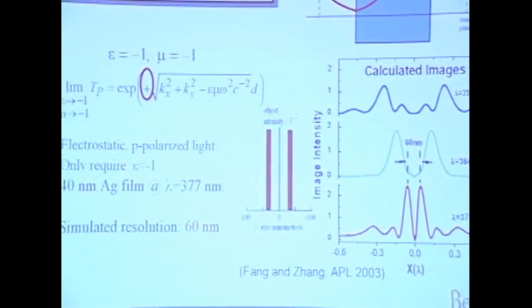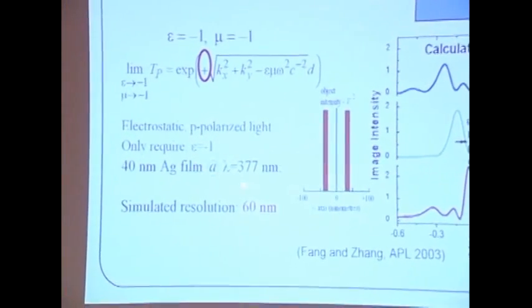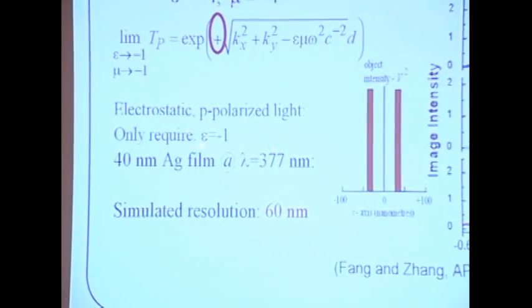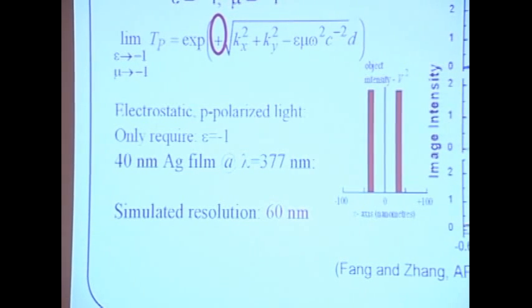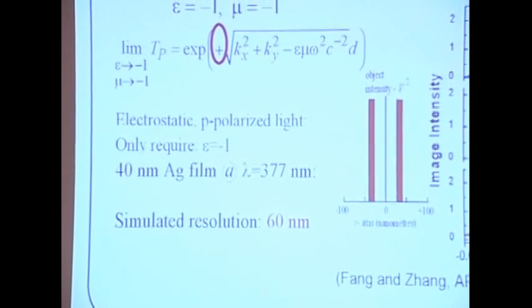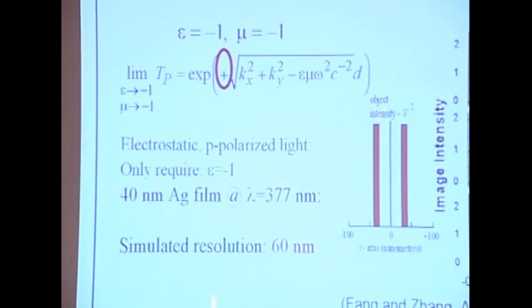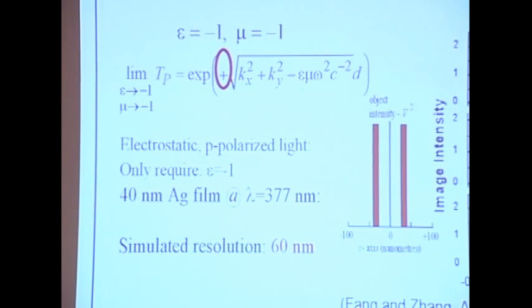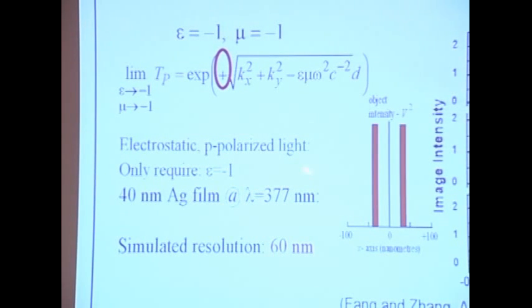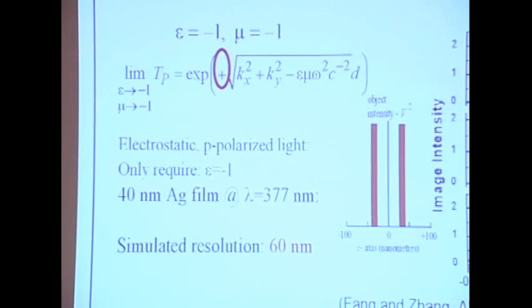But this actually brings an interesting electrostatic limit where everything is smaller than the wavelength, so you can work only with epsilon. You can forget about the mu. And that gives you a special case of this negative index. So you can use a piece of metal, such as gold or silver, which itself is not a negative index medium, but could give you very easily a negative epsilon.